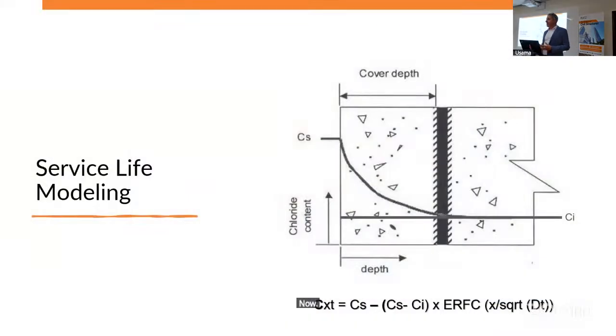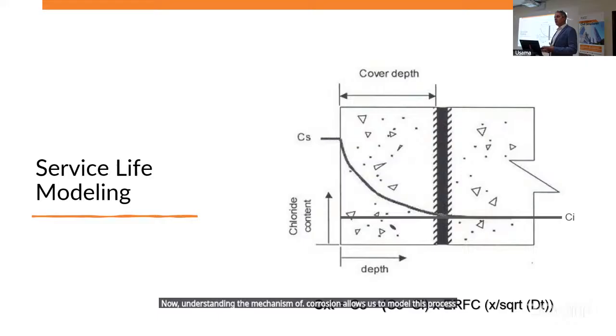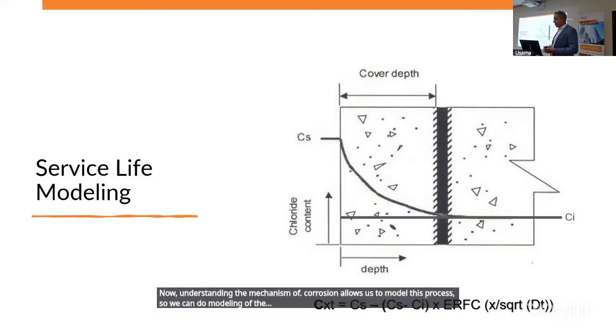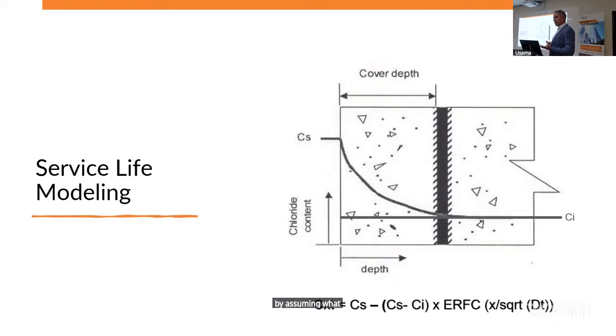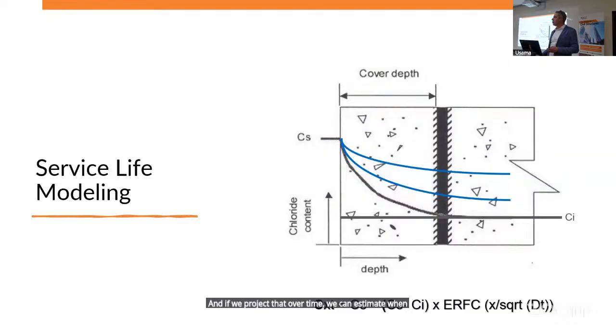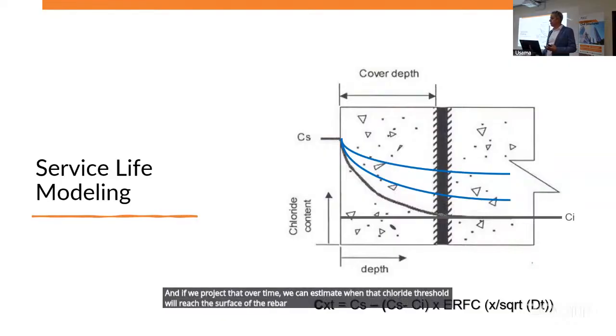Now, understanding the mechanism of corrosion allows us to model this process. So we can do modeling of the service life, of the time to failure for reinforced concrete structures, by assuming what the surface chloride is based on data that we have from the field, knowing what the concrete cover is, knowing the quality of the concrete. We can start calculating the profile of the chlorides within the concrete over time. And if we project that over time, we can estimate when that chloride threshold will reach the surface of the rebar and corrosion starts.